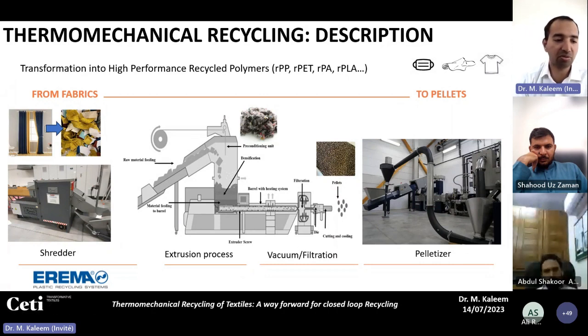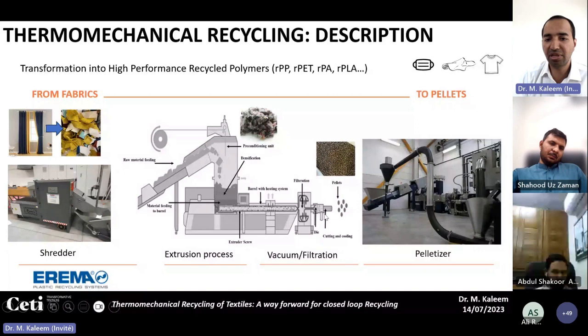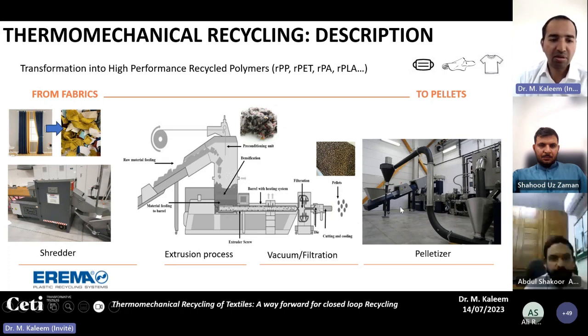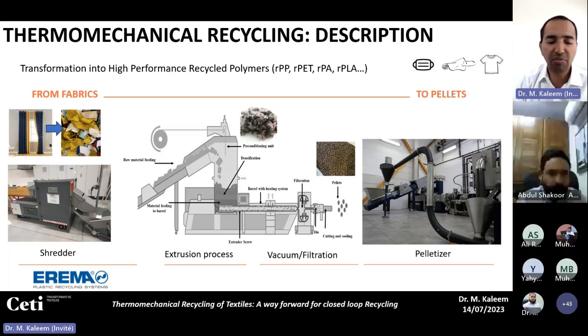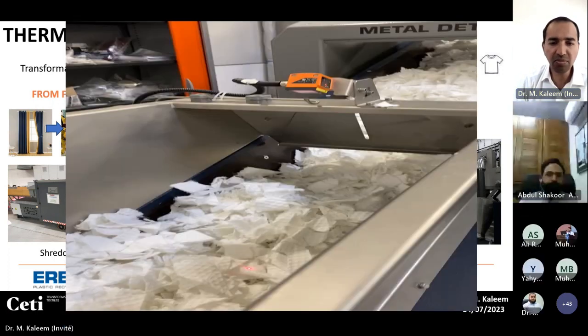Because these days, if the contamination is too high, we cannot process the materials. But if it goes well, at the end after filtration you have a pellet collection system, and the melt stream is transferred into pellets. This is a machine from EREMA that we have at CETI, a complete thermomechanical recycling process.